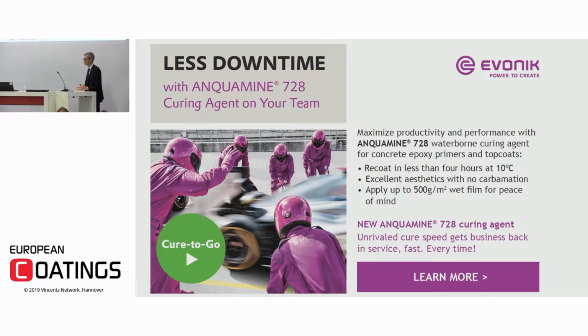So we've developed a new curing agent that allows very fast cure speed with a return to service within 4 hours at 10 degrees. You still get excellent aesthetics. And in addition, you can apply up to about 500 grams per square meter. So it's quite a robust system. And that ties very well into what customers are looking for today in new product development.